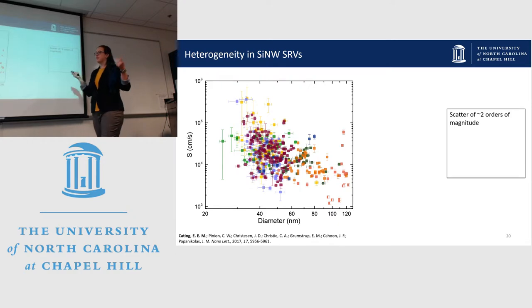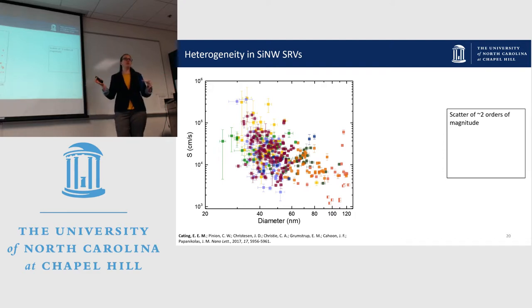You might notice there are a bunch of different colors on the graph. This is because all the wires that I looked at were grown under identical conditions, but they were grown in 8 separate batches. So each batch is a different color. But what you can see is that the scatter in any batch really mimics the scatter in the population as a whole. So this sort of confirms that it's reasonable for us to combine it all into one data set.